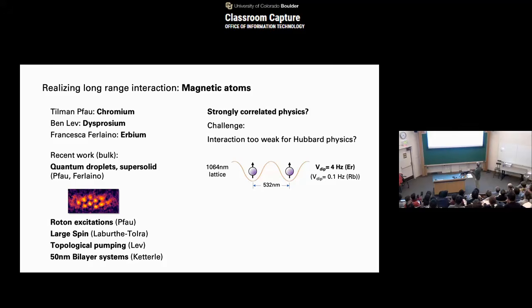If you use erbium, you have a bit more. You have like 4 Hertz interaction, but it's still quite low. What Francesca Ferlaino showed already is that this scales with 1 over r cubed, right? So if you use green light instead of infrared light for the lattice spacing, you can actually boost it by an order of magnitude to about 30 Hertz interaction strength between neighboring lattice